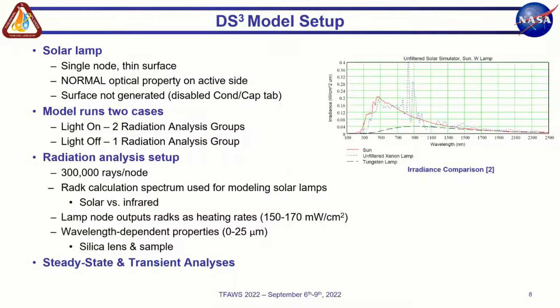And I also disabled the conductance capacitance tabs so that there were no thermal effects from the solar lamp surface besides outputting radks as heating rates, which is an important feature of the solar lamp. And it emitted light intensity from 150 to 170 milliwatts per square centimeter. This was the same range that was used in the test for the DS cubed facility.